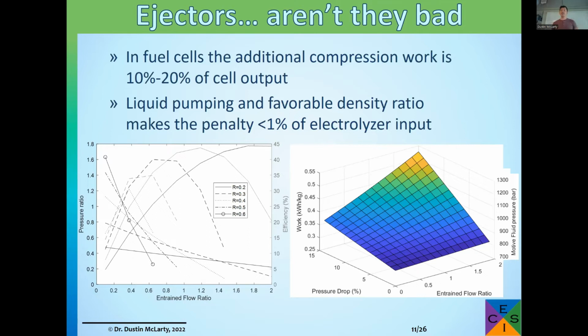And you also end up with a very favorable density ratio between your motive fluid, which in this case is steam, and a mixture of steam and hydrogen as the entrained fluid, which is a lower density. So you get this very favorable density ratio, which improves the efficiency of an ejector, and the fact that you're not compressing a gas to provide the motive pumping power. So even in the worst case scenarios, the ejector in a high pressure electrolyzer is still going to account for well under 1% of the total electric input to the electrolyzer. So it's a nearly negligible impact having that ejector, which is nice, because now we have a solid state part that will never break and can handle the high temperatures very easily.